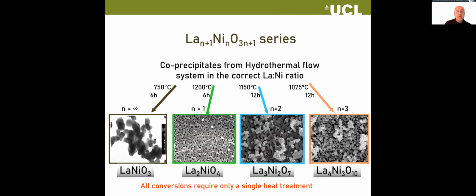Now, one of the things we did do, and this was published a while ago now, so I'm not going to dwell on it, is this series of materials, the lanthanum nickelate series. These are mixed ion conductors, both oxygen ion and electronic conductors. And these are notoriously difficult to make, particularly the 4310 or the 327. These take 14 days of heating and grinding for some of these materials. What we showed was if you made an intimate mixture of lanthanum hydroxide and nickel hydroxide as a co-precipitate, as long as you were at the right temperature, and in this case, I've listed the thermodynamic temperatures at which this occurs. So if you're any higher or lower than that, you may not get the right phase for long enough.